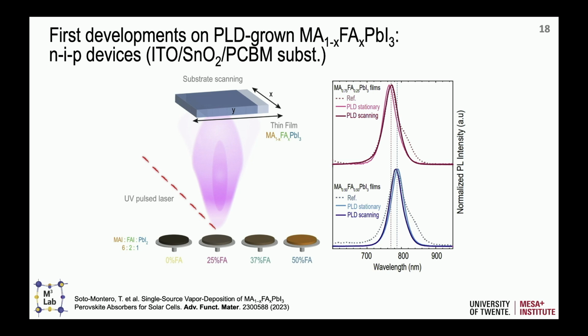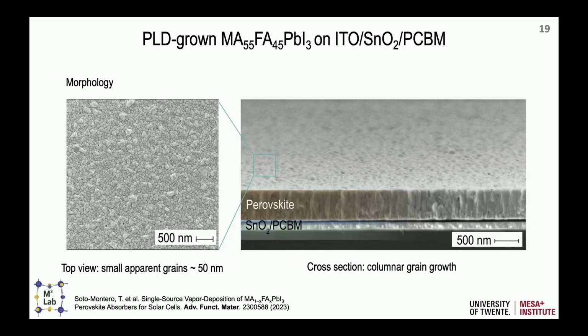And what we show is that by tuning the amount of FA in the target, we can also tune the amount of FA in the thin films. And we can demonstrate this by the shift in the PL. So this is the photoluminescence emission. And of course, if you change the MA and FA ratio, your band gap of the material changes. So that was one of the first demonstrations, just basically on photoluminescence and the band gap. But of course, you also want to know the composition. So that will be the next slide.